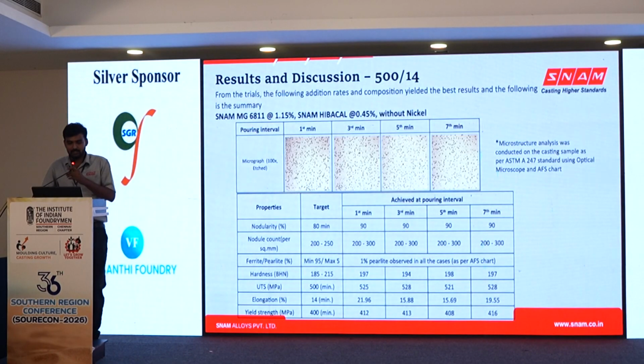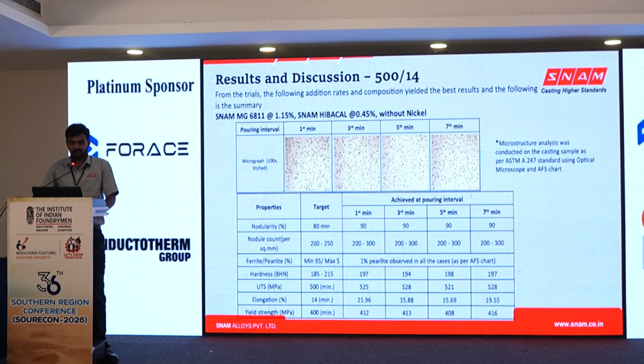The table shows mechanical properties and metallurgical properties at different pouring time intervals. We have achieved nodulity of minimum 90%, and pearlite percentage is only 1% as per the AFS chart. We have also achieved minimum tensile strength of 500 megapascal, and hardness is also within the range.